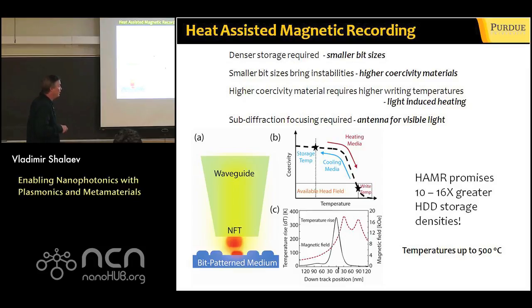But locally, when you heat, the temperature goes up to, let's say, 400 or even 500 Celsius. And nanostructured gold cannot sustain this temperature. Again, that's a problem. If you replace the gold antenna with titanium nitride, for which this temperature is nothing, then of course that could be the solution. You basically change the material, but it makes a huge difference for this important industry. So that's yet another interesting application which we pursue in our group.